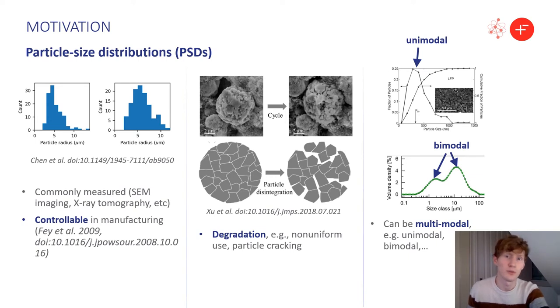The particle size distributions, or PSDs, are actually commonly measured, and you can have some control over them in the manufacturing process even. They could well play an important role in degradation, and change over a cell's life if larger particles crack and disintegrate, such as for NMC. They can also be multimodal, meaning they have more than one local maximum, and this turns out to be an important aspect one should account for when modelling them in this context.